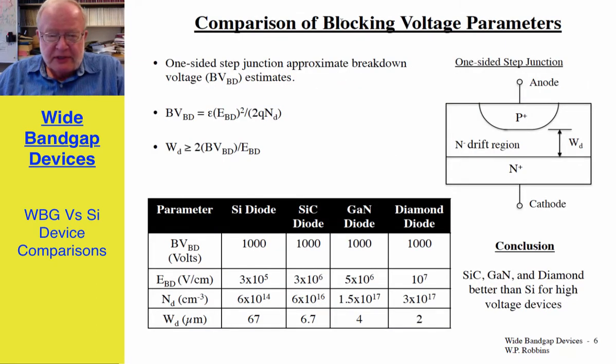For example, let's consider a simple example of calculating the blocking voltage capability of a PN junction. I'm assuming a one-sided step junction. It's not too difficult to show that the breakdown voltage is proportional to the square of the breakdown field strength divided by essentially the doping density. And the drift region thickness has to be greater than twice the rated breakdown voltage divided by the breakdown field strength.